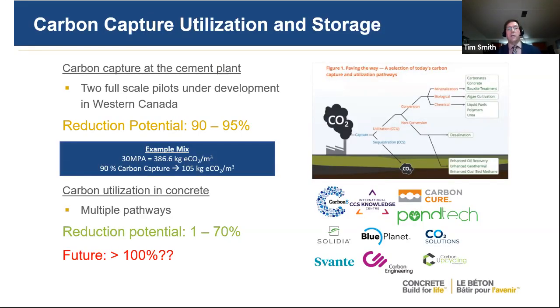Now, another important area is carbon capture, utilization, and storage. There are two main areas here that we look at. There's carbon capture at the cement plants, where we can capture the CO2 that's being emitted, and that can either be stored down in the ground, or it can be utilized to create other products. Such as Blue Planet, they have a system where they take the CO2 and produce aggregates out of it. So there's a lot of research out there right now, and there are some forms such as Solidia that use less energy to produce the cementitious material as well. And then you get CarbonCure, another technology, which injects carbon into the concrete as a way of utilizing the CO2. So there are a lot of ways. The carbon utilization in concrete and the carbon capture are areas that we're spending a lot of time and effort researching.